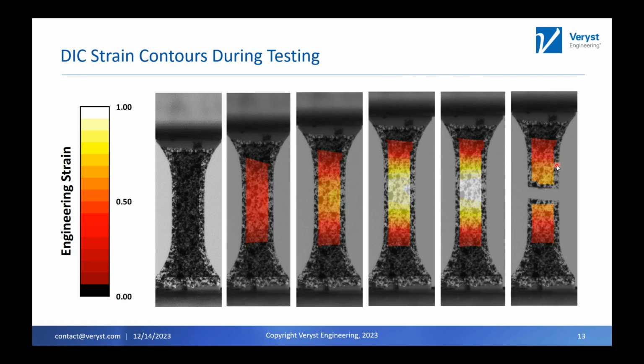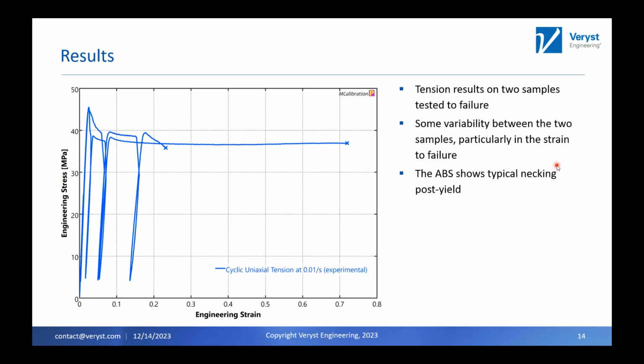So the strain field looks okay, Sean, but what does that mean to me? Here are two results on samples from the same brick done at a strain rate of 0.01. We like to do what we call SMART or advanced testing here. That's that cyclic testing where we go up, we hold the strain, we unload, then we reload. So you can see here we have two repeats. These repeats look very similar to each other.